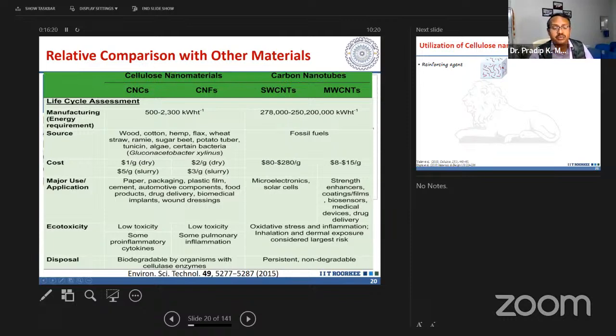But the most important parameter I want to tell you is that after disposal, our material will not create any problem for the environment. Rather, the carbon nanotube material you use during its application as well as during its disposal is not degradable at all. That's why the health hazard as well as the pollution to the world will be very, very high compared to our material. So wherever carbon nanotube cannot be replaced, definitely we will use the carbon nanotube. But if the required mechanical properties are at a lower limit, then easily we can replace it. In BMW cars we use graphene, carbon nanotube or carbon nanofiber, and we are targeting to replace them with cellulose nanofiber.